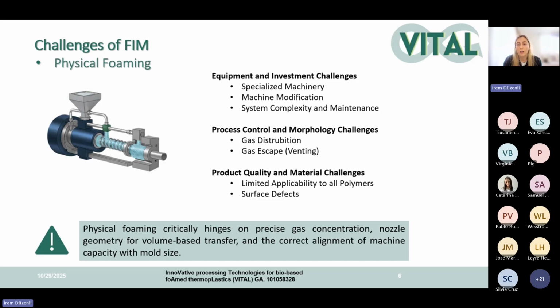Process control is also important in this process because you need to distribute the gas homogeneously to get good quality parts, and sometimes you can struggle with gas escaping from the molds. There are also product quality and material challenges, because you have limited applicability to all polymers, and you can see some surface defects on the parts. Key points are the amount of gas and process optimization, like temperature arrangement. It's very critical, and you also need to consider whether your machine and your mold capacity are suitable for physical foaming.